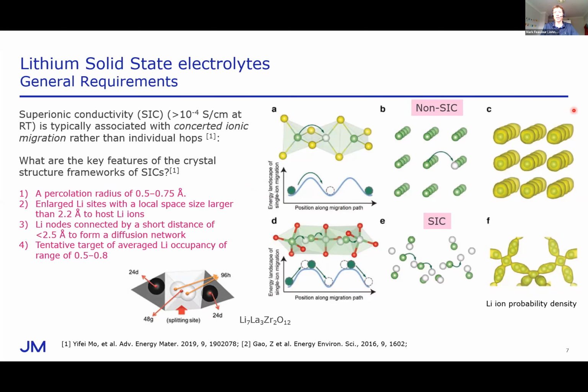So if we look at these sketches of a non-superionic conductor, classically you have an ion in a low energy situation, and it hops to a vacancy nearby through a transition state over an activation barrier, as shown again here. But the lithium ion probability associated with that process is solely located around the lithium ion sites. In contrast, a superionic conductor has a much flatter energy landscape profile.